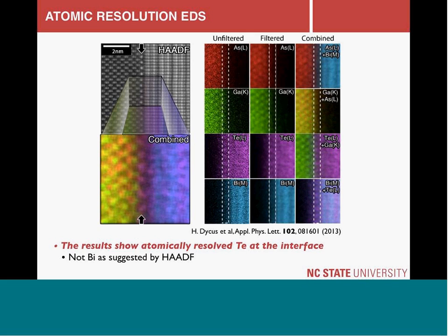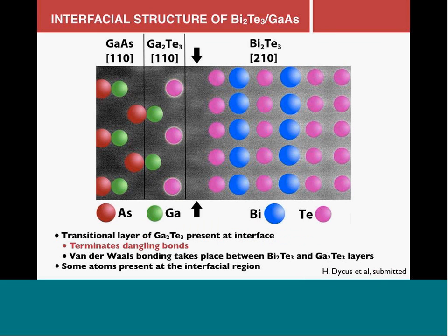Okay. Seeing that map, we get this beautiful example: all those purple locations there are the atomically resolved, perfect, beautiful interface that we've been able to explore previously. So what that means is that at the interface between these two materials, there's a second phase forming, or a third phase forming, a quarter unit cell of gallium telluride structure.